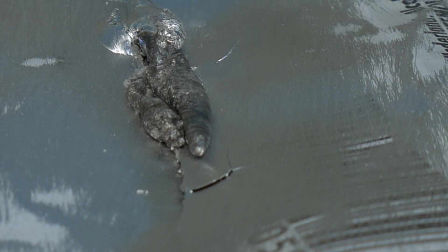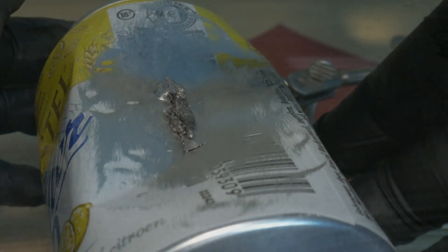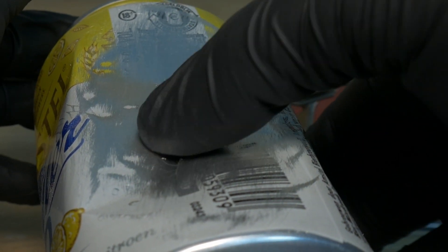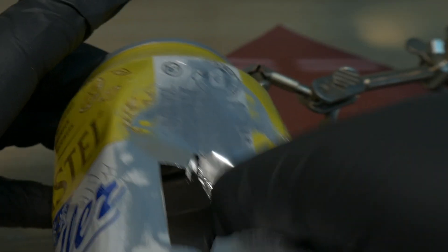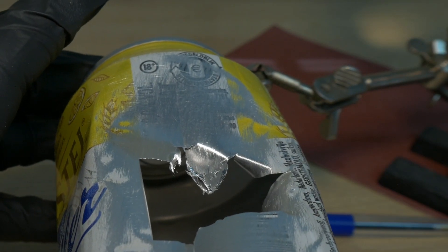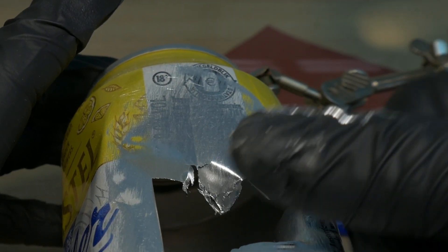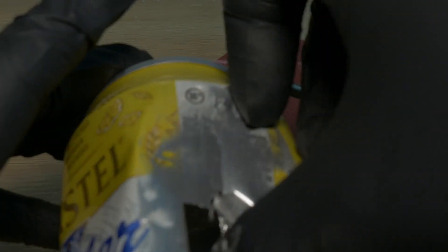Now aluminum is actually a very reactive metal but in everyday life it doesn't corrode that easily because it's always covered by a thin aluminum oxide layer. Think of it as aluminum's invisible armor. Gallium's superpower is that it can penetrate or disrupt this oxide coating. Now when we sanded the can or the metal piece, we gave gallium a way in. Once the gallium is in contact with the bare aluminum, it prevents the aluminum from healing its oxide layer. It's like gallium pulls off the aluminum's armor and won't let it put back the armor.